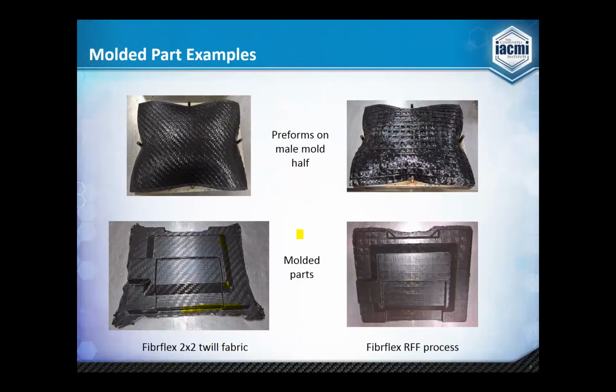So they're both placed on the male portion of the tool. The female portion was laid on top of that, manually pre-compressed. We placed that in an oven, brought the tool to the melting point of the resin, transferred it to a compression press, and applied pressure to close the tool, cooled it, and took it apart, and at the bottom you can see the results. The fiber completely wet out. These things rang like a bell, so they're very well consolidated. We were quite pleased with it. Both parts formed well. There were some significant differences, and that's what Mike will be talking about next.